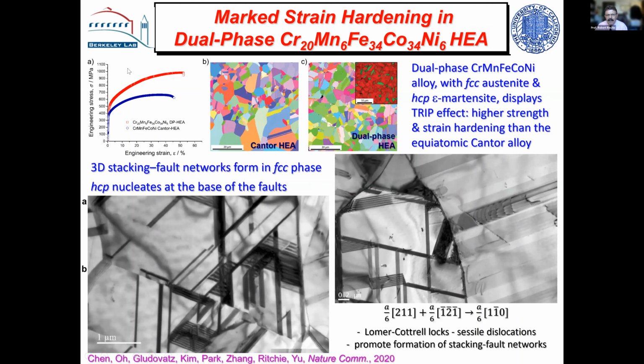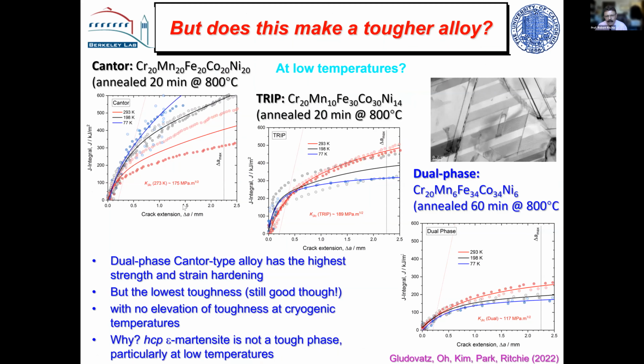This is the original Cantor alloy. These are R curves, J integral versus crack extension. Red is warm at room temperature, green is dry ice, and blue is liquid nitrogen. And that's the one I showed you before, that you get this increase in toughness at liquid nitrogen temperatures. But when you have this TRIP effect to form the hexagonal, be it dual phase, or you can do it where it trips itself during the test, you get good toughness, but it doesn't get tougher at these lower temperatures. So it's a very similar composition.